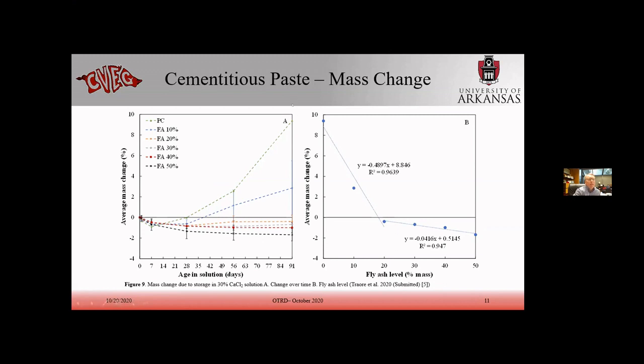You can see that here at 91 days of age in the salt solution, we gained about 9% for the control mixture. You add 10% fly ash, the gain is only about 2.5%, 3%. And the other ones basically remain the same, maybe a 1% decrease in mass. You can see the noticeable decrease from the control mixtures down to, as we increase fly ash, this average mass change decreases. The average mass change was 9% for the control mixture without fly ash, and as you add fly ash, the mass change decreases.